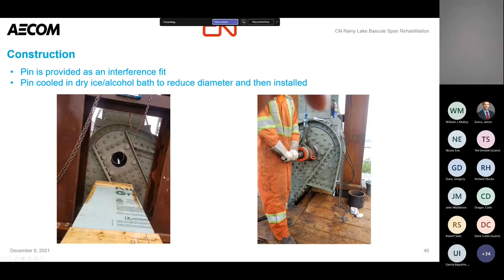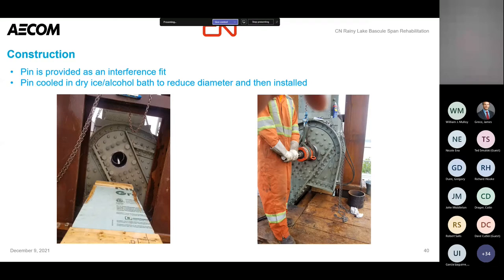Installing the pin itself — it's an interference fit, so the pin is larger than the hole. The way to get it in is by cooling the pin. They built a little cooler on site, filled it with a mixture of alcohol and dry ice, dipped the pin in, and it cools such that it actually gets smaller than the hole. You then pull it out and get it through. This is one of the more intense things you see on a movable bridge site — you have a limited window because if you get it partway in and it heats up too much, it clamps in place and you can't move it. Then you have to hydraulically remove it, which cold-works the surfaces, tears the steel, and you're essentially back at square one.